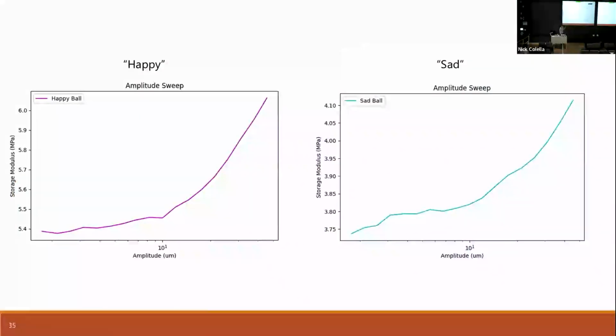So we can get some data for these two rubber balls, and we can do an amplitude sweep first. So this is as you push more into the ball, how does it respond? This is exactly to your point earlier. So if we have small amplitudes, up to about 10 microns that we're indenting on the sample, we get pretty consistent moduli. It feels about the same in terms of how stiff it is. As we start to go up to 100 microns, then we see, okay, all of a sudden it takes a lot more force. It's a lot stiffer of a material in terms of the storage modulus.